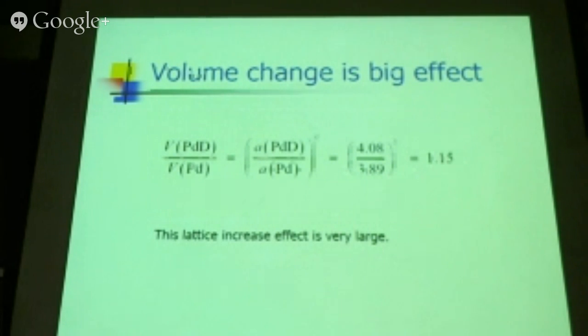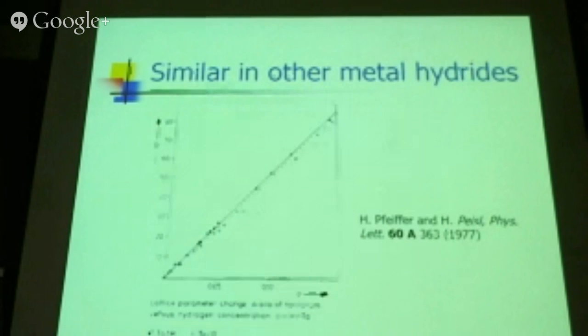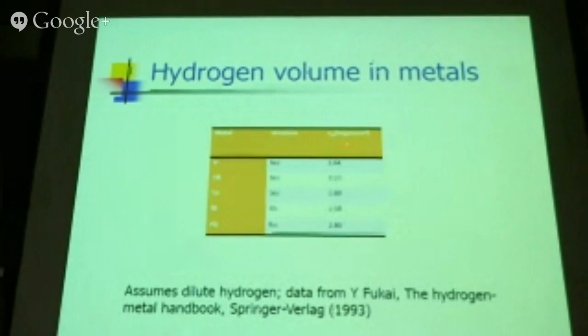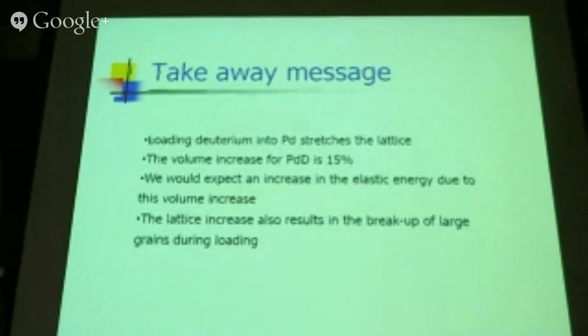It's about the most intensive thing you can imagine doing to a metal. You're stretching the bonds apart, with such a large volume increase. Loading other metals with hydrogen also gives a volume increase, so this is not particular to palladium. So here's a table of volume increases for hydrogen for different metals: palladium, nickel, tantalum, vanadium, niobium. You get similar numbers, so there's nothing special about palladium. And you imagine that you put hydrogen in the palladium and stretch it out. As it stretches, you're going to need more energy to put more in. That means that you would expect it to be harder to load the more hydrogen you put in.